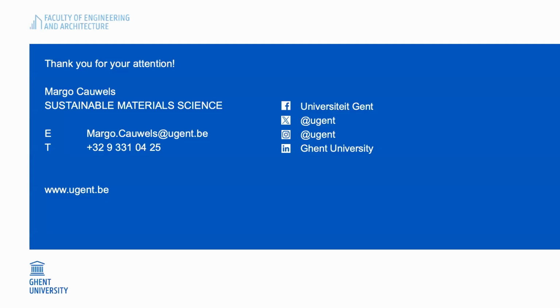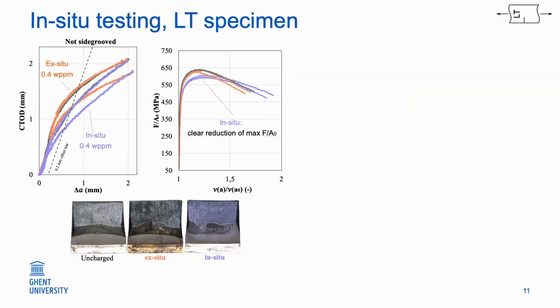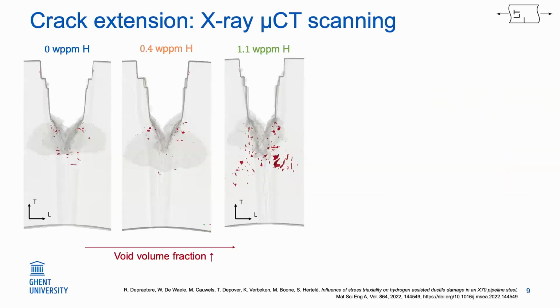No, so the void generation is not random, it's very linked to the equivalent plastic strain. So we can actually see these two wings of the butterfly. That's the region where we really get this enhanced void formation. And also it is a lot at the inclusions, which is where you normally get the voids, but especially where we get the really big ones that really show in the CT scans, the hard bands are very sensitive. I think especially the martensite islands, because they have the very large strain incompatibility with the surrounding matrix.